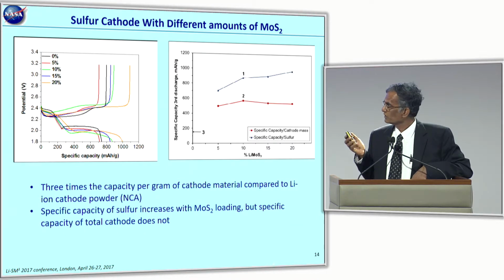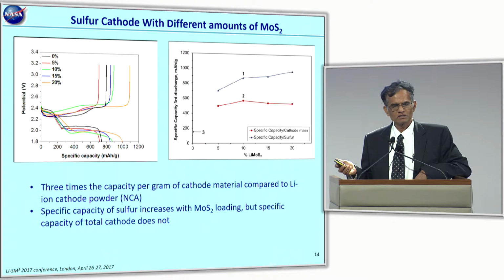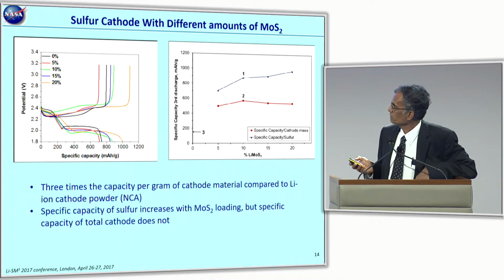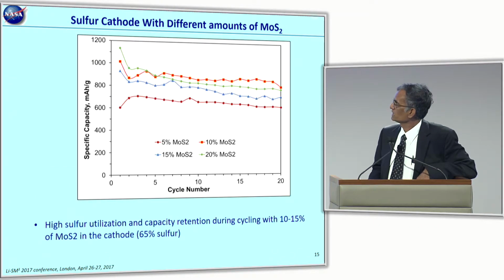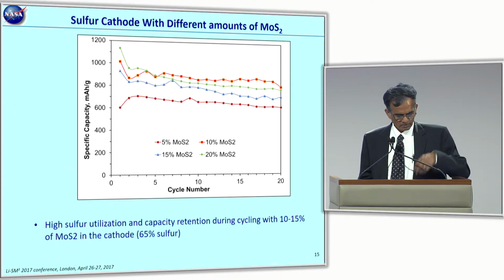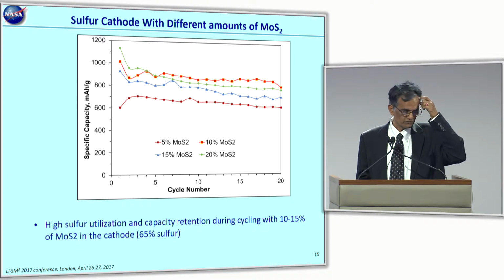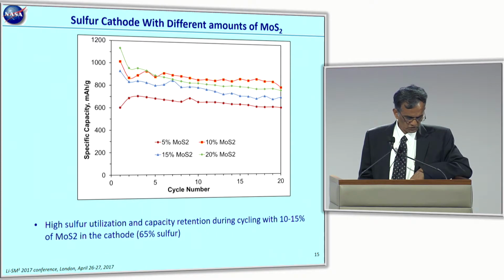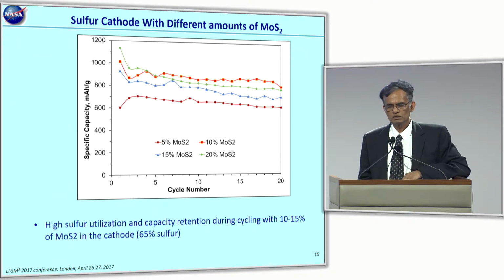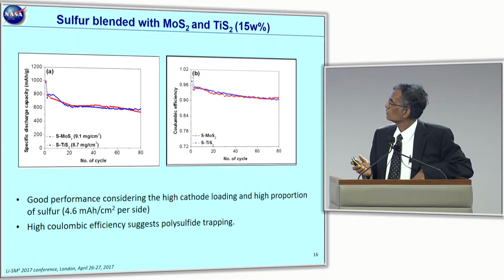And so obviously going to much higher percentages like 20% will affect the capacity. But if you stay within that 5 to 10%, there's actually a benefit in terms of utilizing the sulfur and getting a higher specific capacity from the sulfur with this kind of combination. Here, we are looking at the cyclability of these electrodes, and you can see that particularly if you stick in the range of 10 to 15% of the moly, you have a decent cycle life combined with better utilization of the sulfur in these high loading formulations.